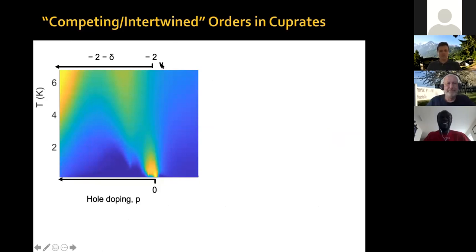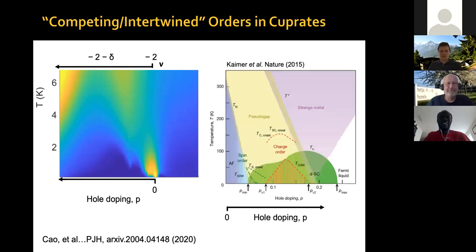So here is a further zoom in this region. This is filling factor now, and here I put hole doping. So 2 holes per moiré unit cell means 0 doping when you want to compare to the cuprates. Now we go to 2 holes plus extra holes, so filling factor -2 minus delta, which is equivalent to hole doping. And you can see that there is indeed that feature there. This is again very reminiscent of this. Remember, here you dope in this direction, here you dope towards the left.